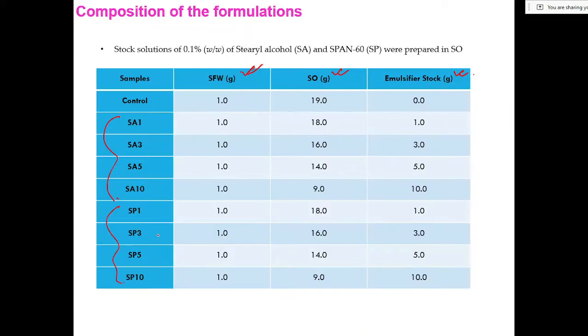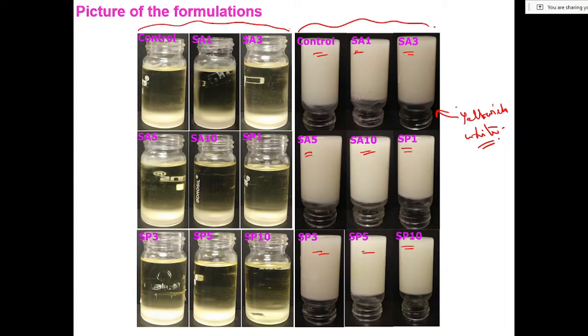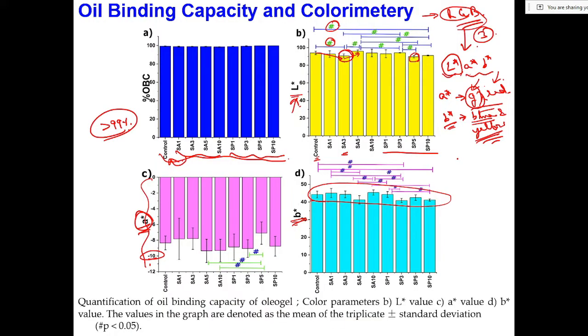Also, if you go back to this sample, it had a yellowish tinge, but it was again yellowish-white in nature. Okay, if you look into the L star values, all of them have an L star value of greater than 90, that is, most of the light is being reflected back. Okay, so due to this reason, the samples appeared white, and due to the higher B star values, the samples had a yellowish tinge. Okay,